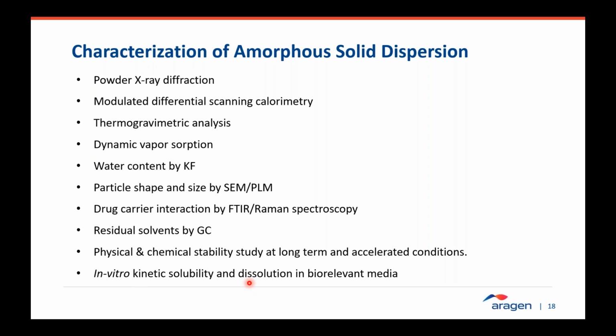So once all these are confirmed, the ideal solid dispersion must be stable, improved solubility over the neat drug, and has acceptable Tg value, typically above 60 degrees, and the drug should be in amorphous state. Those are the criteria based on which formulations are selected for the PK studies.